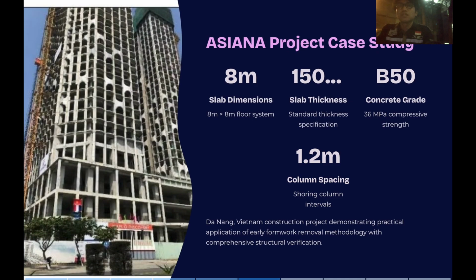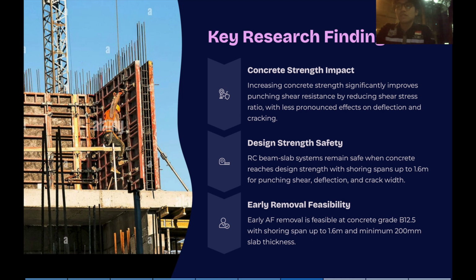And then this is the case study of the Asiana project. To put this into practice, let's look at the Asiana project in Da Nang, Vietnam. This high-rise project utilized a B50 concrete grade, 36 megapascal compressive strength, with 150 millimeter slab thickness and shoring column intervals of 1.2 meter. The project successfully demonstrated that early removal is not just a theoretical concept, but a practical methodology that works in high-density urban construction.